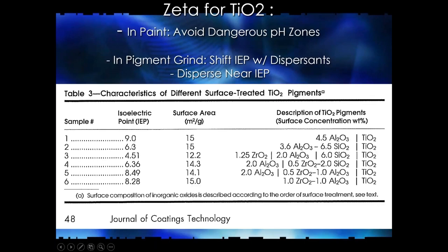So the isoelectric point is the point of zero charge. And what happens is these particles are clumped together. You wind up with shaving cream. This is the danger zone. Where is the danger zone for your product? So if you're trying to disperse your product at an 8.5 pH with raw titanium dioxide, good luck. If you're dispersing it below 9, you're going to have no problems. This one is the interior grade, the one with a 9 pH IEP.